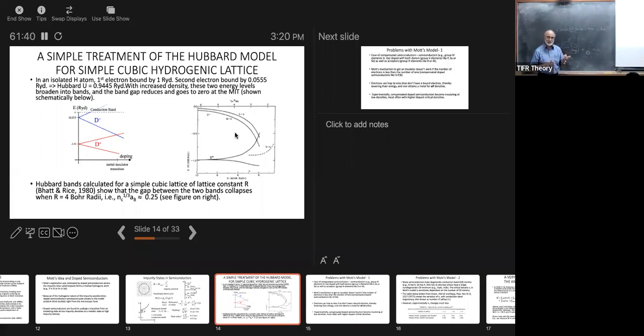That's nature. It's another reason why, Krishnamurti asked the question, why is N_C to the 1/3 times a_B equal to a quarter approximately? If you write it as N_C a_B cubed over a_0 cubed, then it's 1 over 64, which is a small number. It's almost halfway to the fine structure constant. Because that number is small, and I have some reasons to believe that nature wants to be metallic and tries to become a metal as soon as it can, that's why that number is small, I think, in reality. And because it's small, a lot of theories that start from the insulating phase actually do very well. If you start from the very nice metal, very fully screened, and try to come to the metal insulator transition, you do much less well. So if you're interested in the metal insulator transition, starting from the insulating side is somewhat easier, I think.